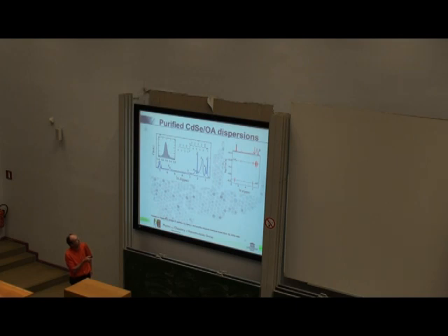What we see is that the narrow resonances all come with a very large diffusion coefficient. That's toluene, a small molecule moving quite quickly in solution. All these broad resonances, on the other hand, have a diffusion coefficient that is about 20 to 30 times smaller than these small molecules, which means that the object is moving 20 to 30 times slower in solution. You can also link a size to the diffusion coefficient, it's one over. So the broad resonances come from an object that is 20, 30 times bigger than a toluene molecule. That's the 5 to 10 nanometers of the nanocrystal. So the resonances we're looking at here are molecules bound to this nanocrystal, and they move together with the nanocrystal in solution. Using DOSY, we can pinpoint all the resonances of bound ligands in this spectrum.